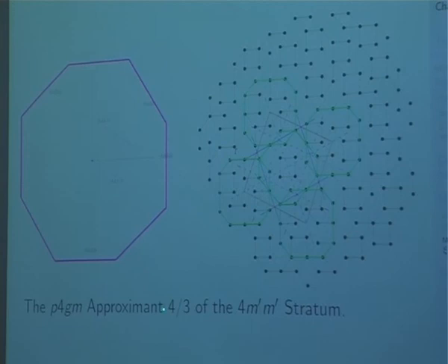So, just for fun, I wanted to show you a more complicated one. Here it's again the 4M prime and prime 4-3, okay? It's much larger than the one we saw. There are not 3 jumps in that case. And we will take the Burgers vector 1, 0, 0, 0, the simplest one. This is a Burgers vector that will take this whole structure, which is quite complicated, and move it just one step. The question is, forget about everything I said, how can you, just by phason jumps, make it move with a minimum number of jumps, and have everything come back?